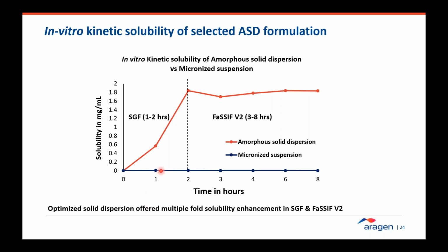So this is an example of final selected formulation in vitro kinetic solubility. So solubility is typically targeted at 2 milligram per ml. And as you can see, micronized suspension almost has no solubility. As we see in equilibrium solubility, it is correlating with that. And the selected amorphous solid dispersion improved the solubility in SGF and then maintained the supersaturation post that in FASIF. It's a two-step dissolution model in the same conditions. We just add the FASIF to the SGF and observe whether drug is still in solution state or precipitating.